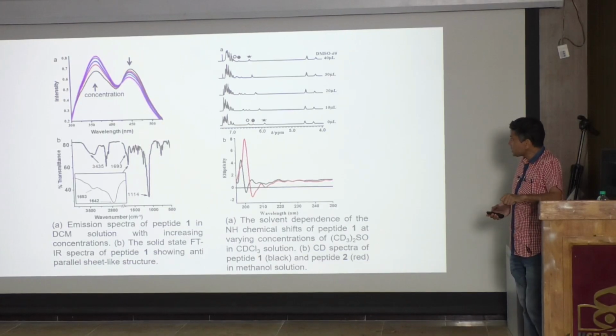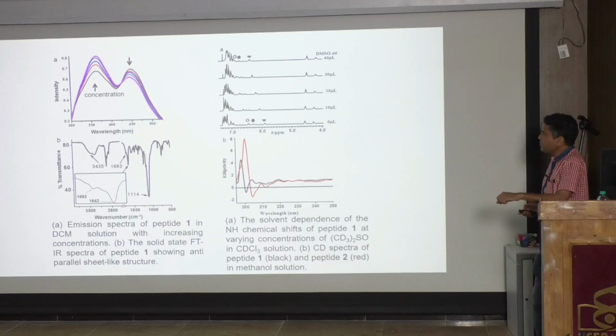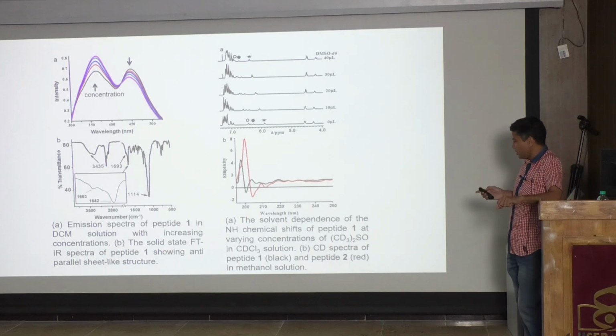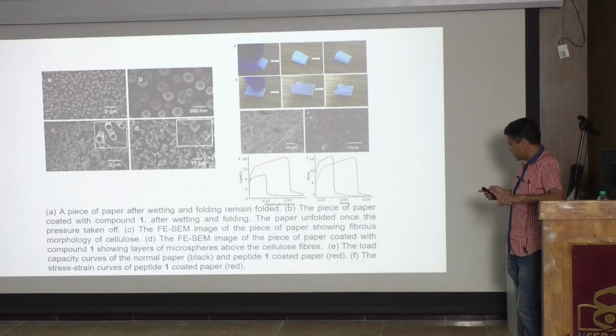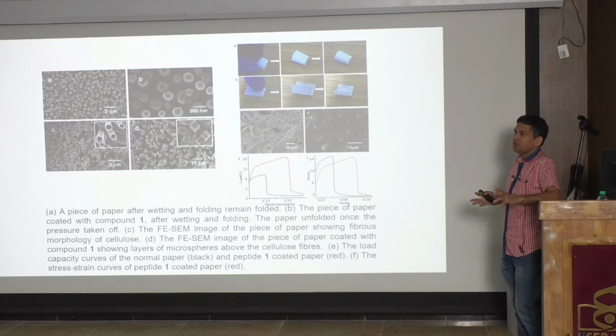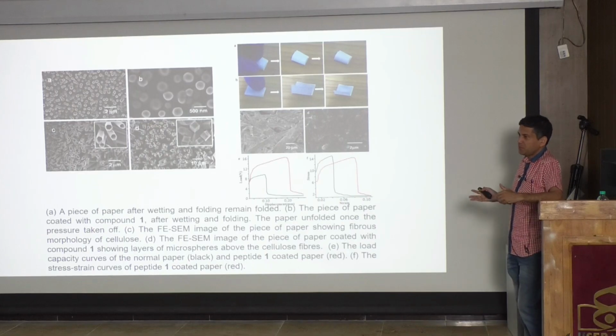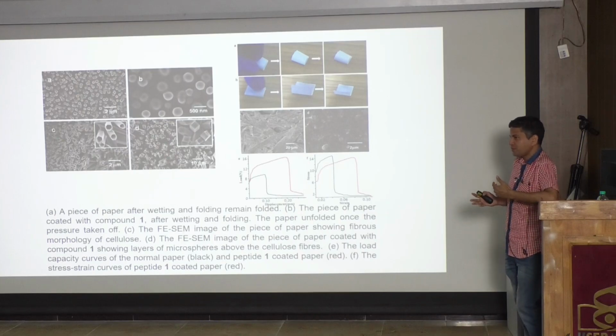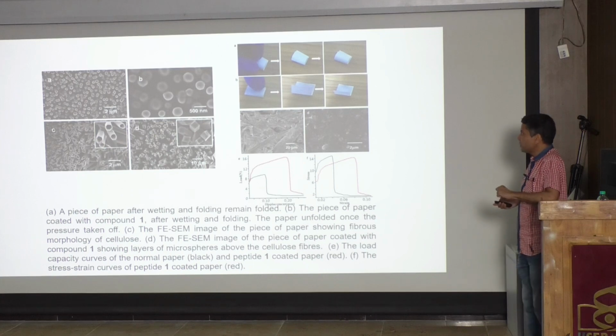So initially we studied that hybrid material with different spectroscopic techniques, and we figured out how the molecules self-assemble, what is happening in the self-assembly pattern. We found that the molecules of the hybrid material are self-assembled in an antiparallel beta sheet manner, with intermolecular hydrogen bonding and pi stacking interactions and all these things. But that is the theoretical background.